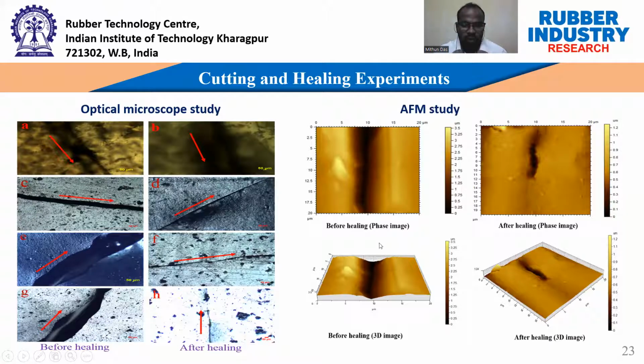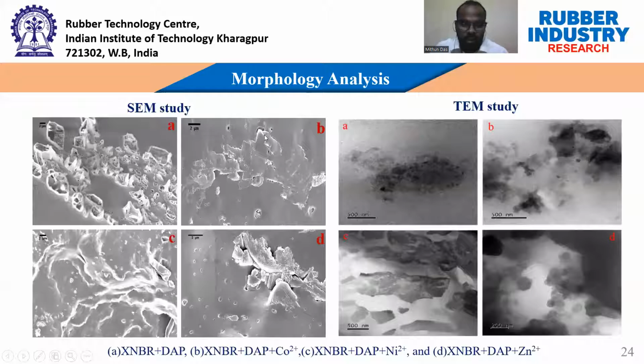And also further we have done the AFM study. In the AFM study, we have only performed the zinc modified compound because zinc has the highest healing efficiency, almost 100%. That's why we chose the AFM study of the zinc modified compound. We have seen from the AFM study that the sample is also completely healed at 80 degrees centigrade after 24 hours. And then we have performed the morphology analysis from the SEM study.